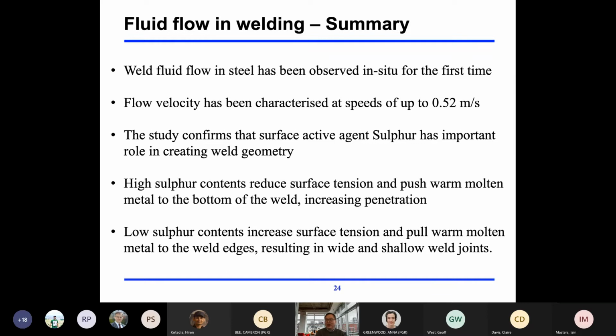And also, if you look at additive manufacturing, arc wire additive manufacturing, you should really think about designing some surface active agents to modify the geometry, and it will significantly affect the formability of your additive manufacturing route. A high sulfur content reduces surface tension and pushes warm molten material to the bottom of the weld, therefore increasing the depth or penetration, and you have a much deeper weld pool or weld bead. And low sulfur increases surface tension and pulls the warm liquid material to the edges of your weld pool and results in wide and shallow weld beads or pools.